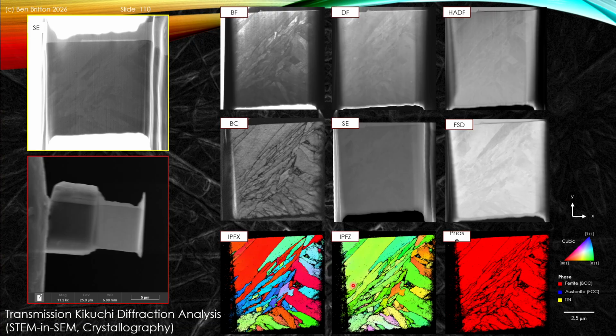In this particular example, we were doing the technique called transmission Kikuchi diffraction. This is basically an EBSD-like method where we can use that to measure the crystallographic orientations and microstructure. So these are the orientations as presented in the phase, and we can look across this structure. This is at very high spatial resolution. Remember that this foil is about 5 micrometers across, and so this was super nice. This is a 2.5 micron scale bar. We can reveal that microstructure with very high precision in here.